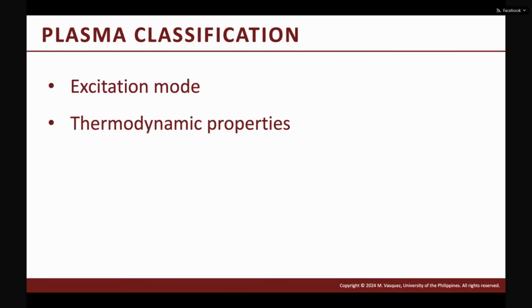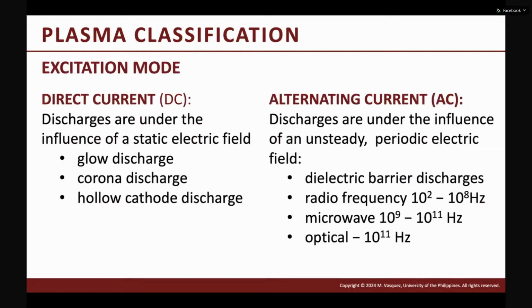Okay. Now, when we classify plasma, there are two ways to classify this, either in excitation mode or in terms of its thermodynamic properties. In excitation mode, if you're familiar with plasma, you can create gas discharges either using direct current or alternating current. So for DC, you can create a glow discharge. If the potential is so high, then you might create some arcs or corona. Another configuration that is also of interest is hollow cathode discharges. If you have alternating current, then you can use dielectric materials like the dielectric barrier discharge to produce the discharge. And then you can have high frequencies to produce the plasma.